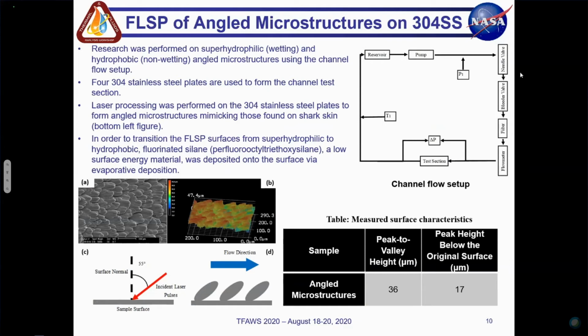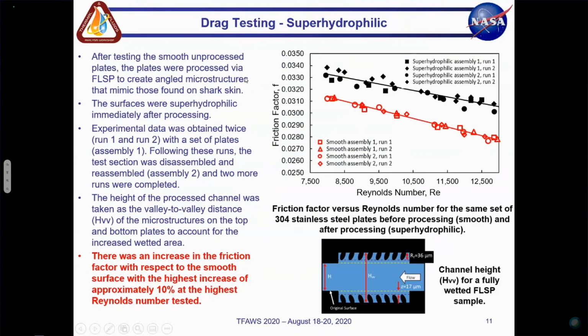Now, after testing these in the wicking or superhydrophilic wettability, we coated them using a fluorinated silane, a low surface energy material, to make them hydrophobic. And that was done using evaporative deposition. The figure on the top right shows the channel flow setup itself, the loop, where you have the pump, the pressures that are measured, how we control the flow rates, and then through the test section, and then the temperature of the water itself is monitored, though it doesn't change much over time.